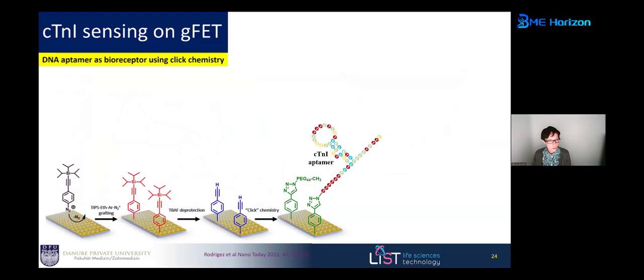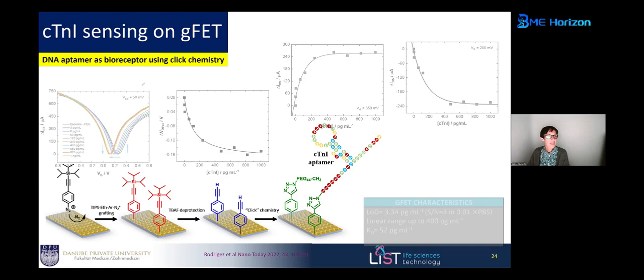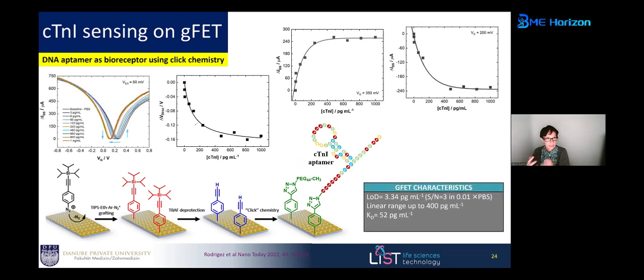So we constructed our gFET sensor. Now you understand the chemistry. The chemistry we used here was click chemistry, and then we used the cTnI aptamer on it to have a small ligand, but we also added PEG units that allow it to work in blood at high ionic strengths. So here you see all the data on these field effect transistors. They work very nicely.